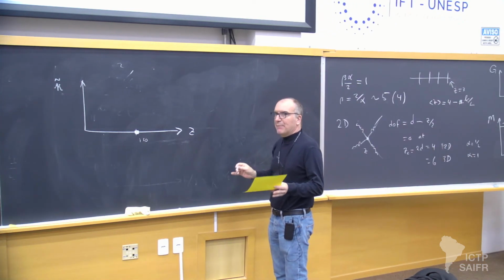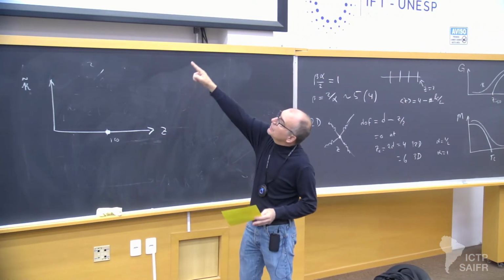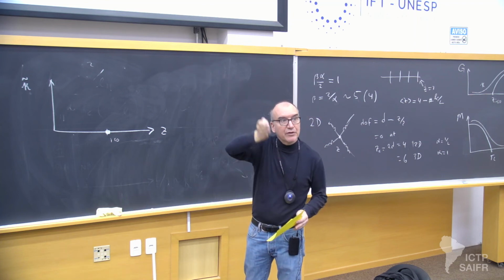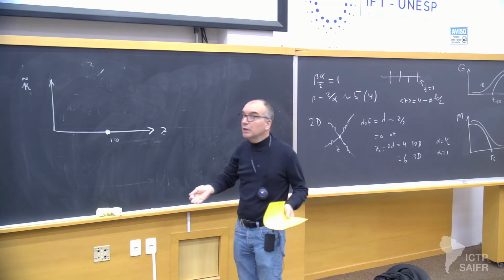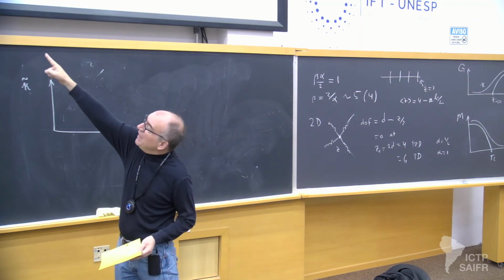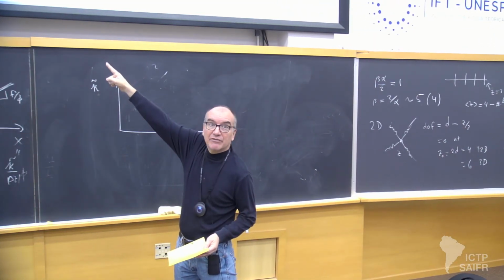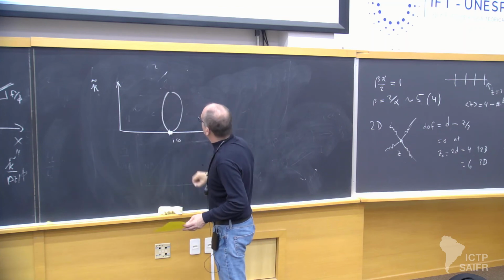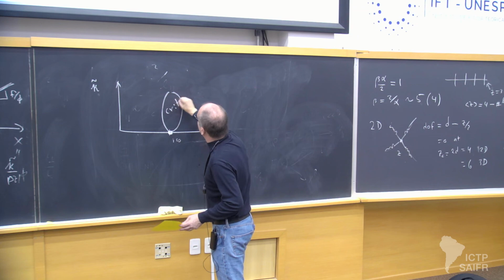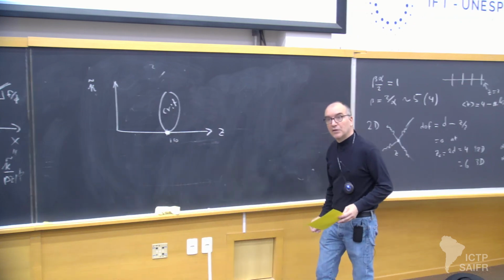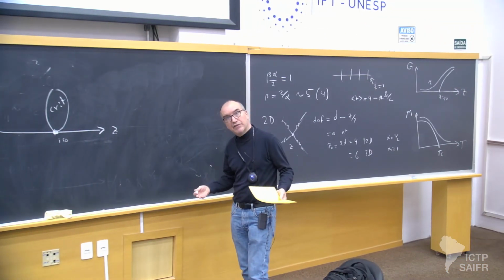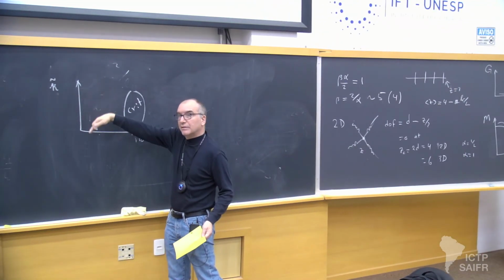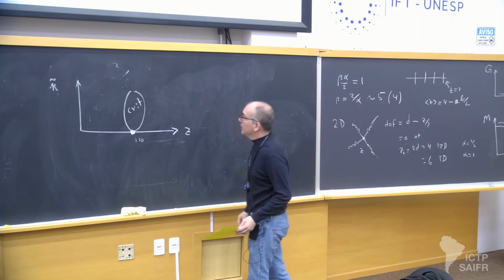At any finite kappa, it's not critical. However, notice those decreasing functions. They're pretty steep near the transition. So you could call that a critical region because they also have peaking or diverging, technically, fluctuations. So you actually get a picture like this with a region which is critical. So you can still see the effects of criticality, even though you don't go through this transition. Again, if you're limited to live with these fiber systems at finite bending rigidity.